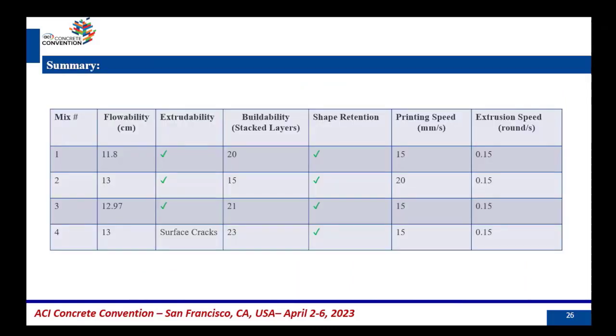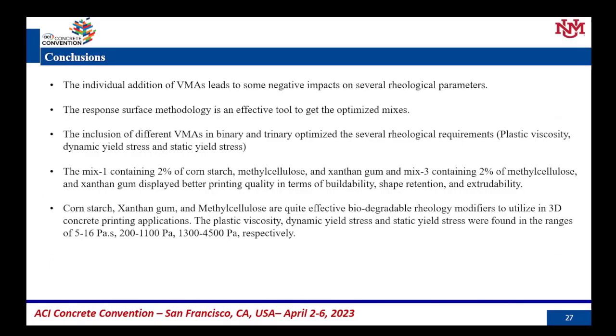To summarize, we get 4 different optimized mixes. Out of 4, 3 satisfy all the printability criteria, starting from extrudability, buildability, and shape retention. And the optimized extrusion speed was the same for all the mixes. And the printing speed was also the same for all mixes except mix 2, where the optimized printing speed was 20 millimeter per second.